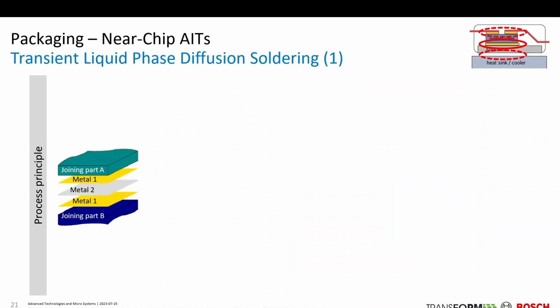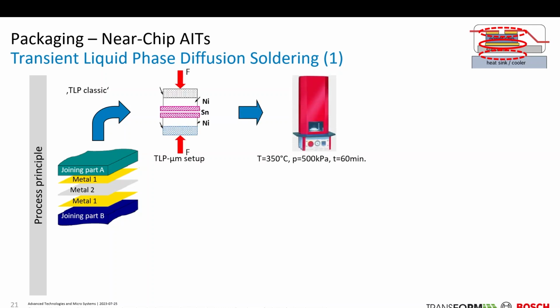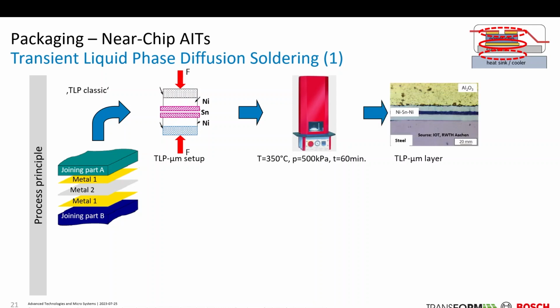Are there alternative technologies available? Yes, there are. You can think about sintering of metals. And this is quite conventional here, the so-called transient liquid phase diffusion soldering. You need a high melting metal, like nickel in this example, and a low melting metal, this is the tin. And then with temperature, pressure, and a certain time of your process run, you have a diffuse layer between your joining partners A and B. Then at the end of the day, you talk about this TLP layer.